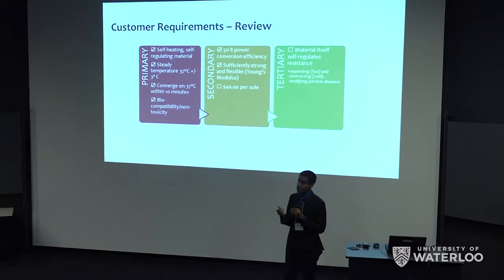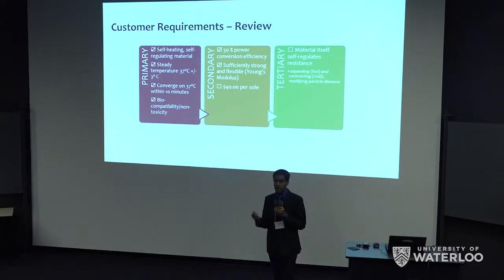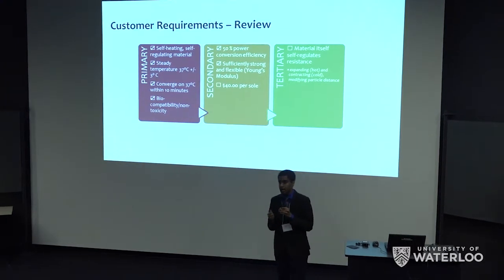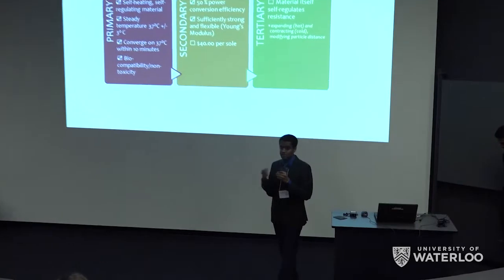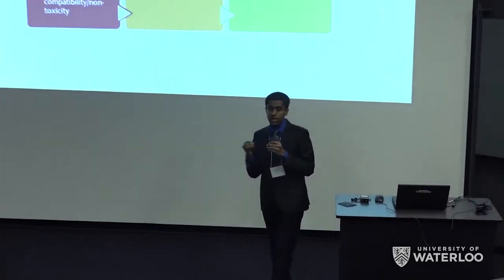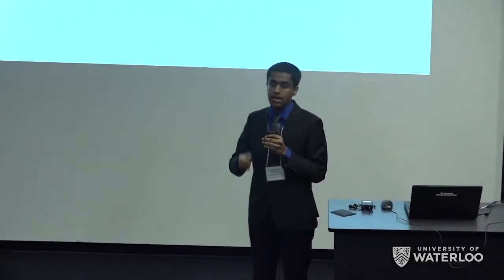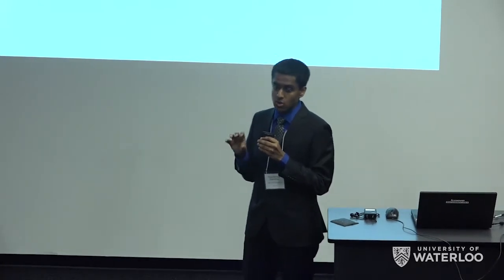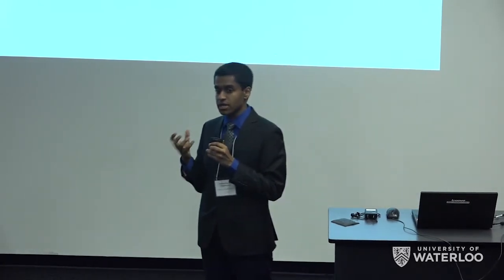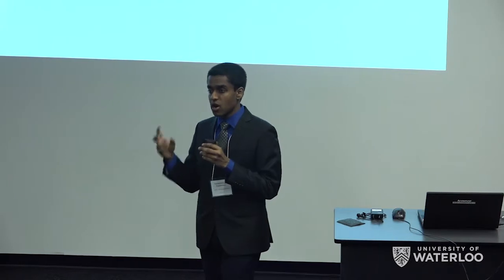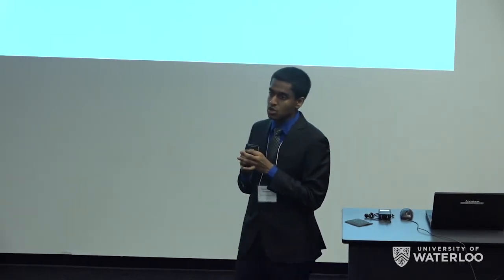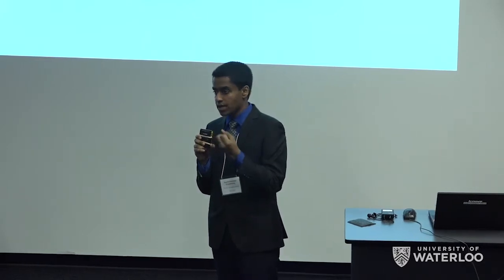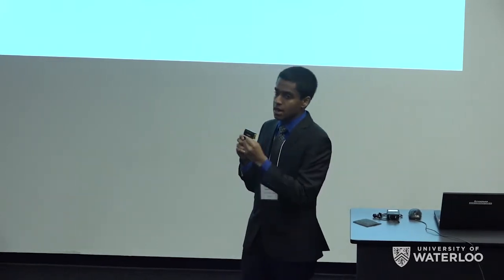One thing we know is that when materials get hot, they expand, and when they get cold, they contract. What this means is that when you have an expanding material, the spacing between each particle will also be increasing, thus increasing the resistance. So we can have a self-regulating material which is smart enough to adjust the resistance on its own. When it gets too warm, it can cool down by increasing the resistance, and when it gets cold, it can heat up because now you're reducing the resistance when the particles come close together.